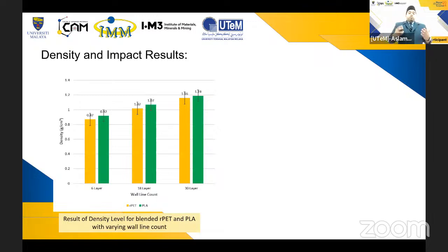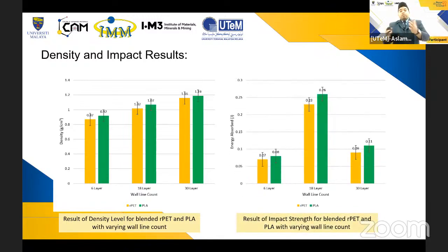So here shows the density level within the blended rPET samples. It shows that the blended rPET is also comparable with PLA, and the SEM images also support the density values with increasing wall line count. However, for the impact strength, the 18 layer wall line count is much higher in impact strength compared to the 6 and 30 layers. This is due to the 18 layer having much better cohesion during the 3D printing process.